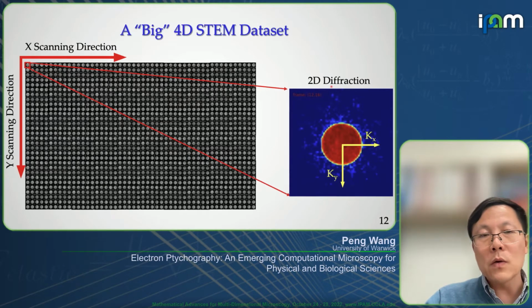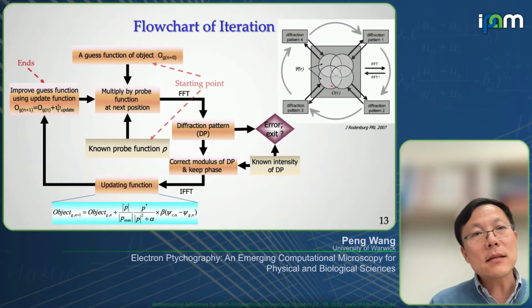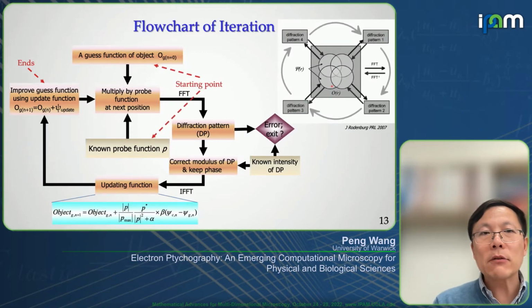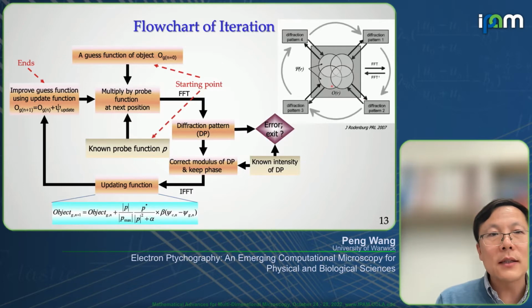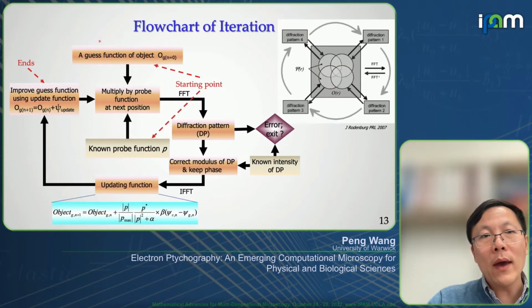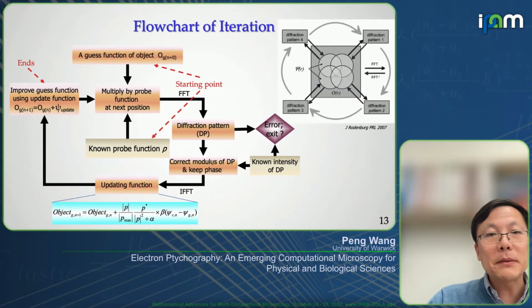But here we use ptychography. This is a very simple ptychography iteration flowchart. As you can see, we begin with a guess function and the probe function. We multiply these two functions together and then Fourier transform this product to the Fourier domain, on the diffraction plane. Because we know the intensity of the diffraction pattern, we can replace the modulus of the calculated diffraction pattern and then keep the phase.